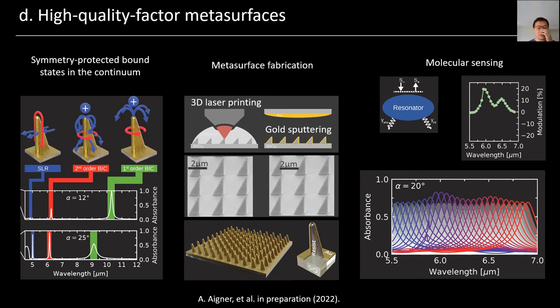This is the example where we can fabricate these 3D triangular nanofin structures, where we can harness the surface lattice resonance, first order, second order, bound states in the continuum resonances that have this high quality factor response. We can break the symmetry using these triangular structures, and by controlling this triangular opening angle, we can easily tune the resonance very broadly across the whole mid-infrared wavelength range, even towards the near-infrared wavelength range.